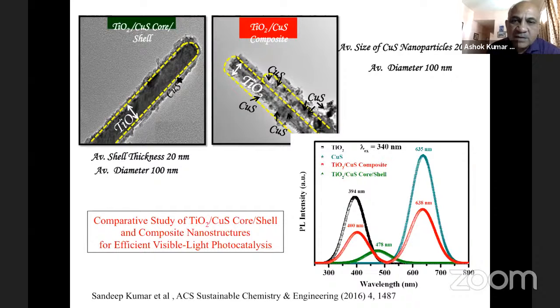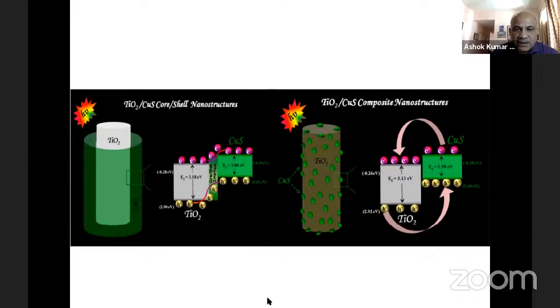Now you don't have a uniform shell. You have more or less particles on the surface. Then you compare their properties. And if you look at the core shell structure, it has much smaller PL intensity, that is the photoluminescence, which tells you that this TiO2 core shell nanostructured material is a better material for your photocatalytic properties and photovoltaic properties.